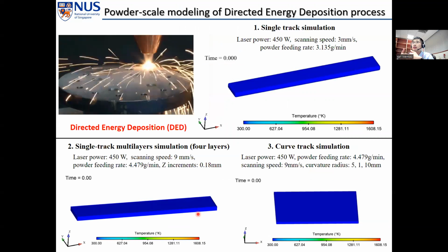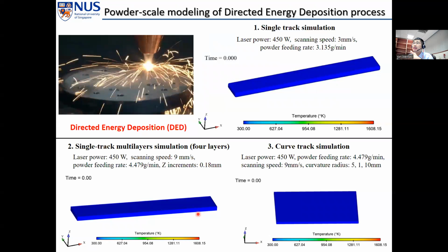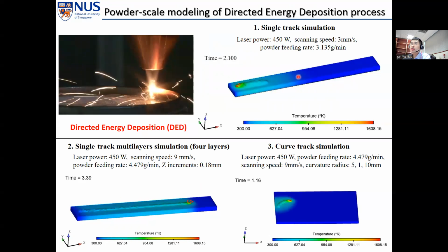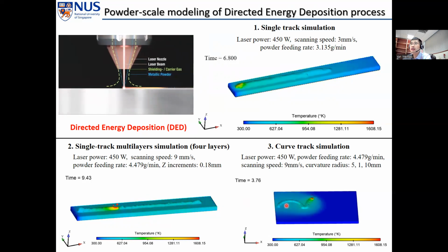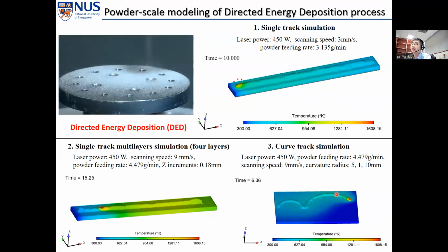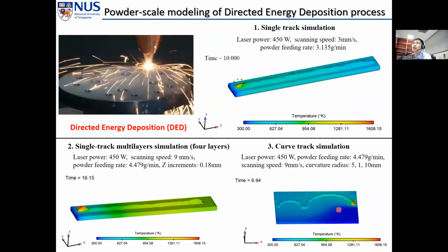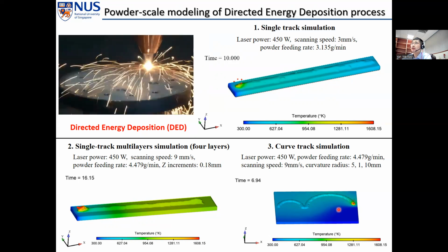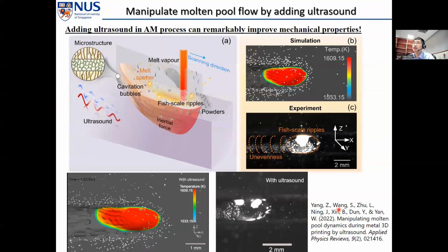In addition to the powder bed fusion process, we also have models for the directed energy deposition process. No matter whether it's a single track or multi-layer, multi-track, or a straight track or curved track, we can easily reproduce it in our simulation. A popular way to manipulate the molten pool flow, grain structure and mechanical properties in this DED process is to add ultrasound. But how ultrasound manipulates the molten pool flow is rarely understood. So we use a high-speed camera to observe the molten pool flow, and we also run the simulation by incorporating the ultrasound effects in our model. You can see the fish scale ripples on the molten pool surface, and this agrees perfectly with the experimental validation.